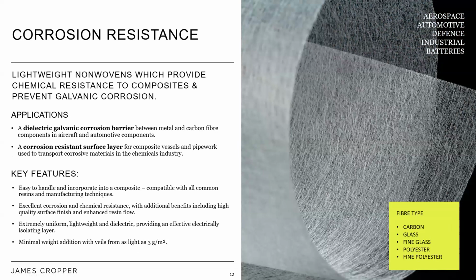For example, where you have carbon and aluminium within the same structure, we want to separate those to prevent galvanic corrosion between the two. The dielectric fibers in a non-woven format provide a structure to do that by separating out those two materials from each other using a tailored thickness and weight. The open structure allows a dielectric resin to fill the voids to form the galvanic barrier region. The isotropic arrangement again reduces stress within the composite parts, and fibers have a comparable thermal expansion to other composite materials, reducing stress.